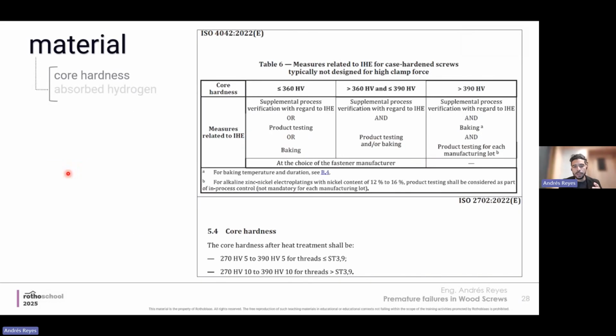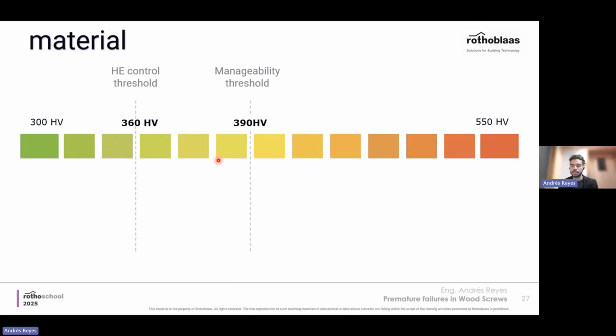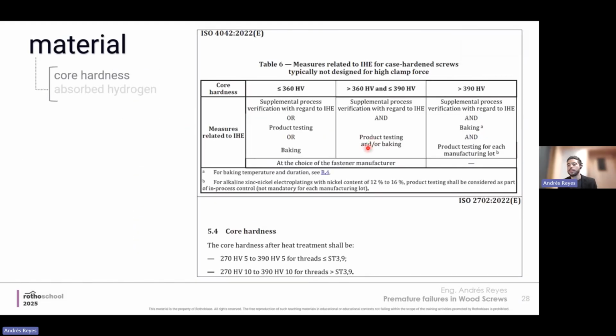So what am I talking about? These are the two standards, 4042 and 2702, that regulate the hardness, the first one depending on internal hydrogen embrittlement, and the second on external environmental hydrogen embrittlement. As you see here, below 360, you could have supplemental process verification with regard to internal hydrogen embrittlement, or product testing, or baking, and the norm even says at the choice of the manufacturer. Then you have this range between 360 and 390, which is more or less an acceptable risk range. And here the norm talks about supplemental process verification and product testing and baking.